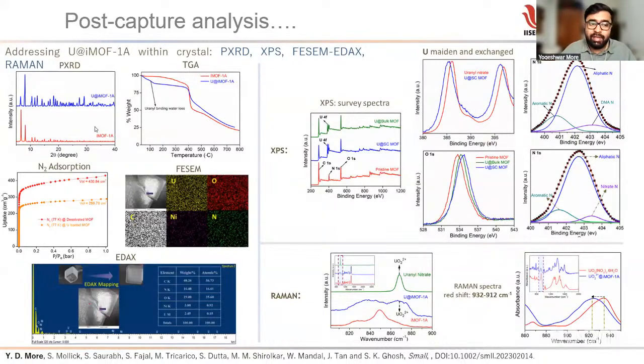So we see after uranium exchange, the PXRD shift is not that great, meaning the crystal structure is not changing. It has a weak ligating interaction. During TGA, you can see the uranyl binding water loss is thin. Here, once the uranium is exchanged, we can see the water loss in TGA, which is because the uranyl cation has extra water coordinated. And then we did the N2 adsorption of the uranium-adsorbed sample. So we saw there is a drop in volume. This 430 cm³ per gram is the original MOF adsorption capacity for N2. And when we did it for the uranium exchange, a drop should be there, because this much of the pore is occupied. Now it is 288.79 cm³ per gram. So there is a gap of nearly 140 to 150. Why this gap? Because this much volume is now occupied by uranium within the pore of the MOF.